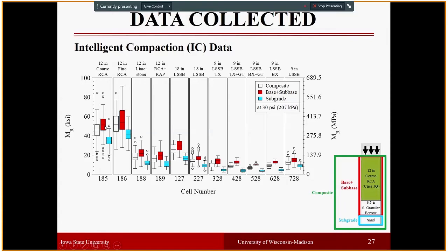And again, as the LWD results, both composite or regardless of the analysis type that we saw, the test sections built with coarse RCA and fine RCA showed the higher resilient modulus values. And 18-inch thick large stone subbases, especially cell 127, provided the third highest performance in terms of resilient modulus. And then class 6 conventional aggregate and the RCA RAP mixes were very identical in terms of their comparisons. And the large stone subbases with geosynthetics performed relatively a little bit lower, provided lower stiffness.